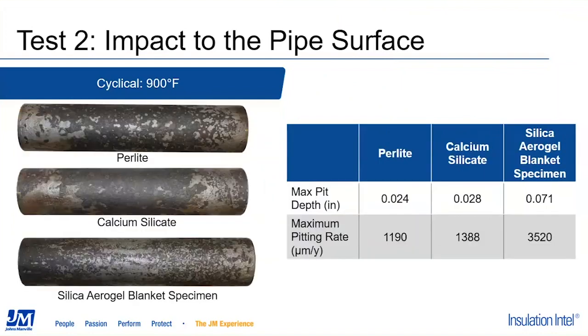We look at the test results of the second test that was run. Again, you have your perlite, your calcium silicate, and your silica aerogel, as represented in the pictures on the left. The perlite's on the top, then the calcium silicate, then the silica aerogel. And that graph on the right is showing us the same thing. We're focusing in again on that pitting and crevice corrosion, that pitting depth. And we can see that the maximum pitting depth in the perlite and the calcium silicate was a lot less than the silica aerogel specimen.